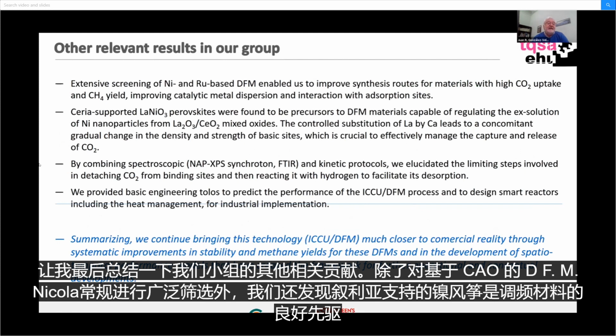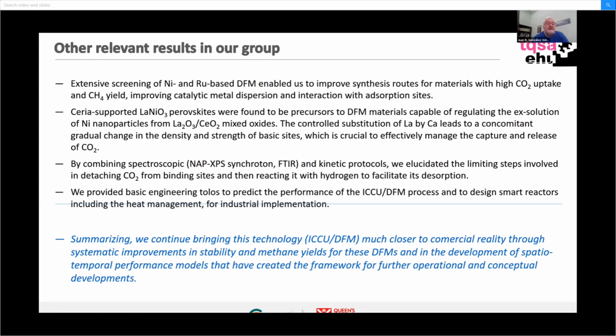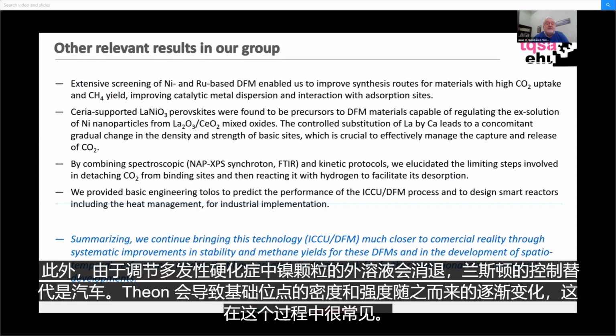Let me finish summarizing other relevant contributions from our group. In addition to the extensive screening of conventional nickel and ruthenium-based DFMs, we found that ceria-supported lanthanum nickel perovskites are good precursors for DFM materials because of regulating the exsolution of nickel particles from mixed oxides. Moreover, the controlled substitution of lanthanum by calcium leads to a concomitant gradual change in the density and strength of basic sites, which is crucial for this process.